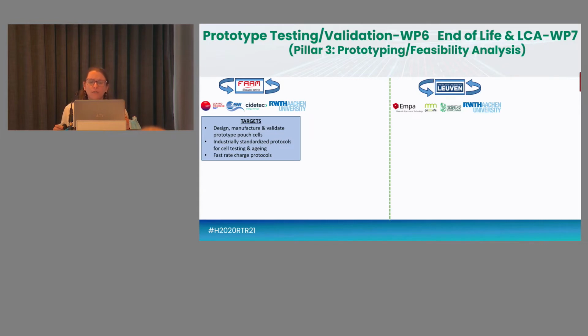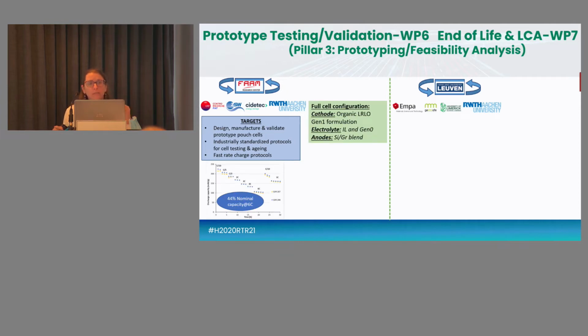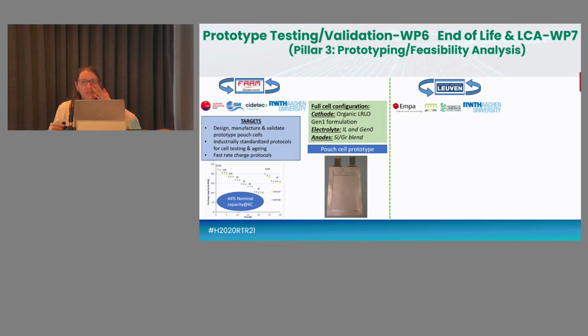By going on to work package 6, which is led by FAM, we are going from the lab scale to a more industrial scale, and they are analyzing small prototypes, and also evaluating industrial protocols for cell testing and aging. Here the main aim is to achieve fast charging for our cell at 6C, corresponding to 10 minutes of charge. And at the moment, these are very initial results that we are having with a silicon graphite blend. But in these months, we are working on testing the silicon anode-based material.